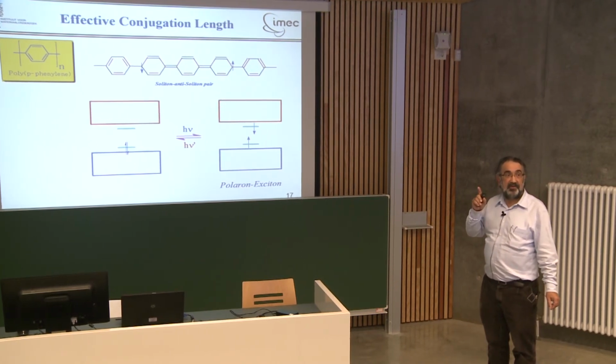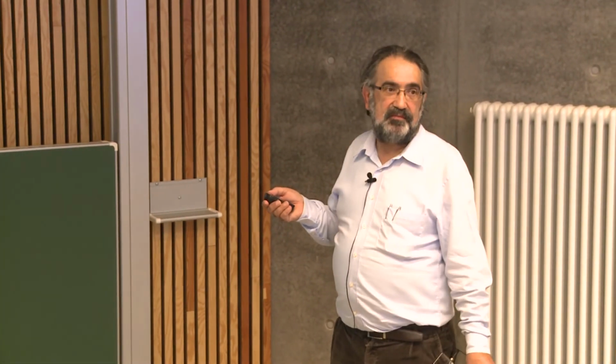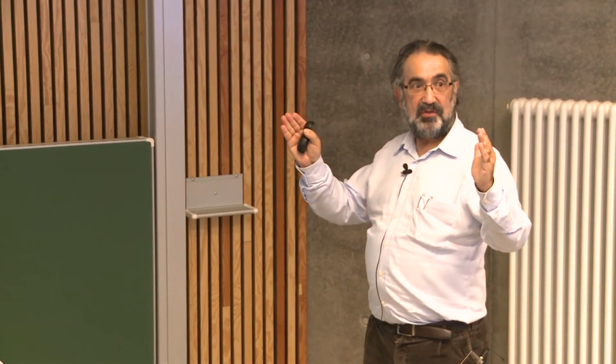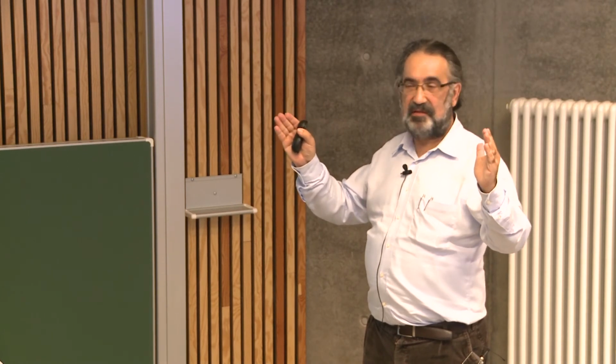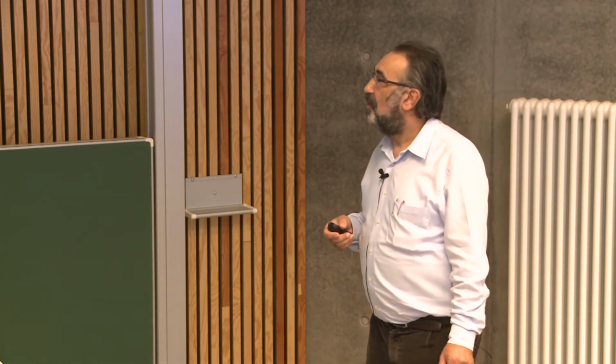So it's over 130 kilojoule per mole per repeating unit. So when you make this intermediate part larger and larger, you will lose energy. So the system has a tendency to confine such an excitation and localize it. So your excited state is localized, and that's the reason why, if you look at the absorption spectrum, there is a limit to the extent to which the onset can shift.